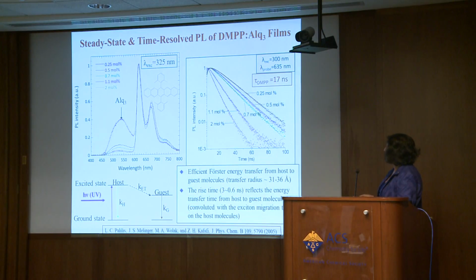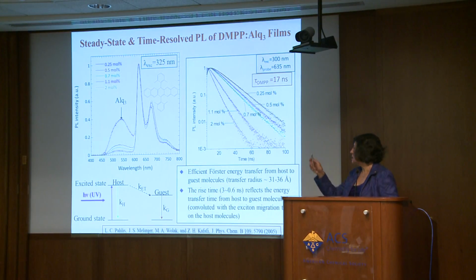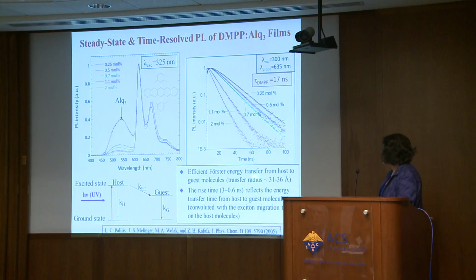So here I show you some fluorescence, steady state and time-resolved fluorescence. This is the host emission, and this is the guest emission. And when we increase the concentration of the guest, you see the emission from the host being suppressed, and the emission from the guest is increased. And this signals that energy is transferred from the host molecule to the guest molecules.